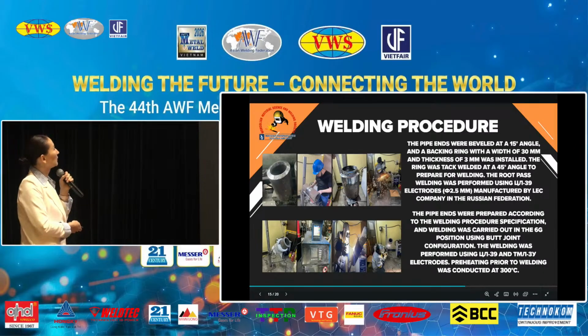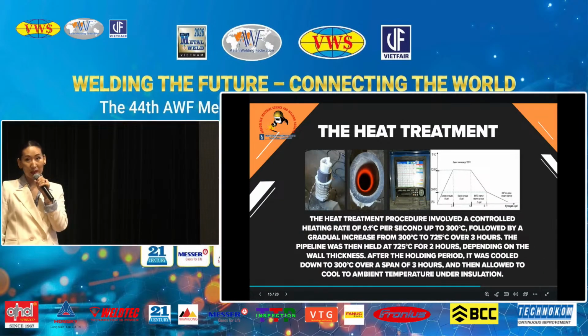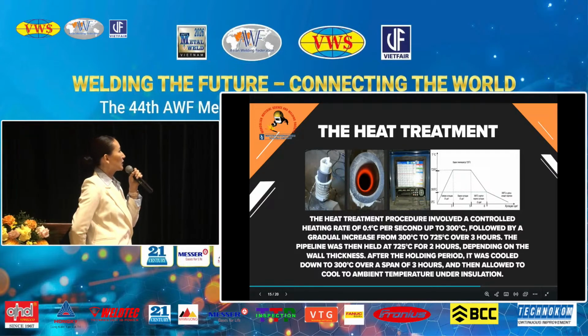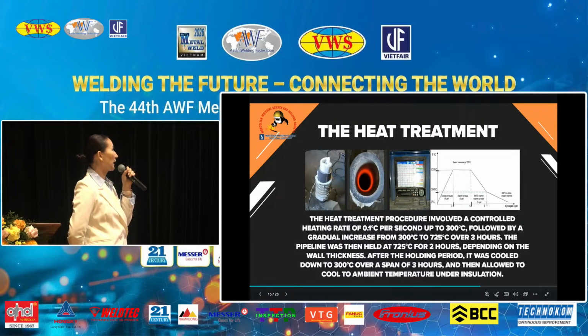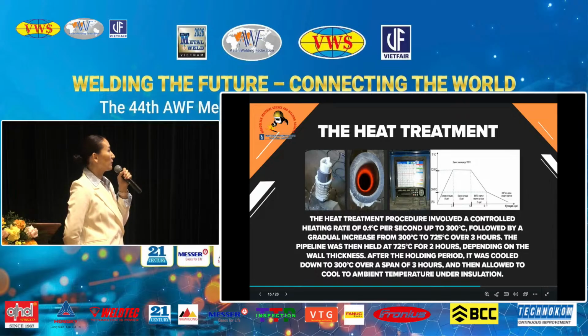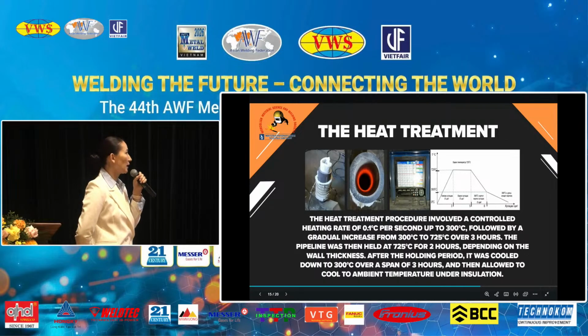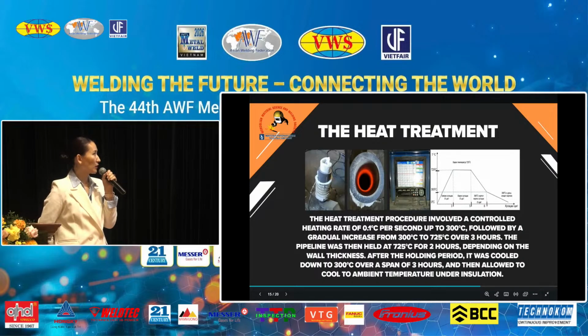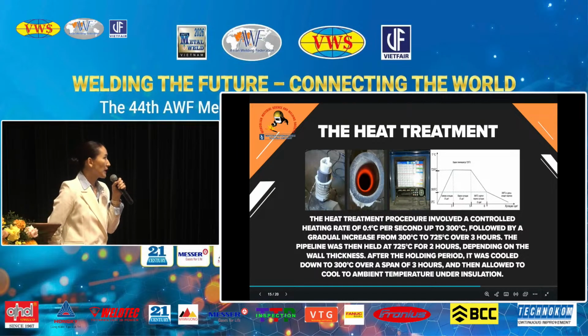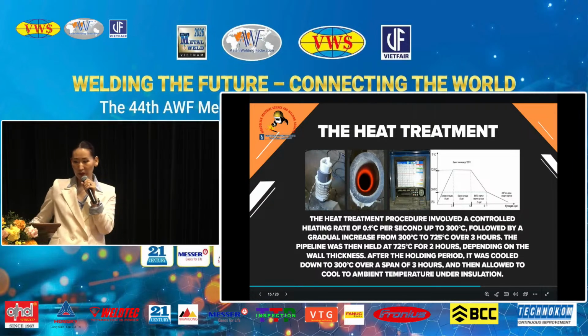Heat treatment. You see there is a heat treatment procedure involved with a controlled heating rate of 0.1 per second up to 300 Celsius, followed by a gradual increase from 300 Celsius to 725 over 3 hours. The pipeline was held at 725 for 2 hours, depending on the wall thickness. After that holding period, it was cooled down to 300 Celsius over a span of 3 hours and allowed to cool to ambient temperature under insulation.